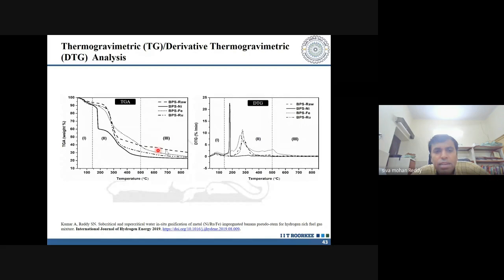So if you see, the nickel is going to result in the lowest conversion, that is less than 25%, and one has to keep in mind this is after loading of the nickel. So if I remove the nickel content also from the biomass, the conversion is going to be less than 10%. Okay, so you see that there is a sharp intense DTG peak somewhere around 300, which conveys that there exists degradation of molecules like cellulose and hemicellulose in this particular portion.